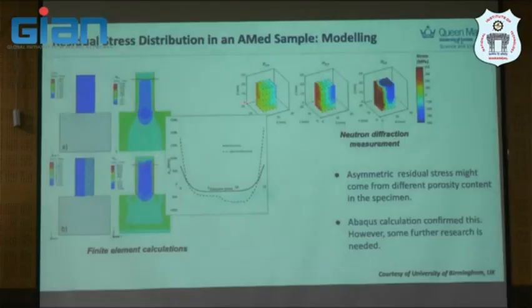So this one, what we try to do, we try to model what happened in the previous slide as well, looking at different microstructural content, assuming that this component has porosity preferred in one location. And this actually contributes to the asymmetry of the residual stress profile calculated in the Abaqus simulation here. And this actually confirms why further research is needed when you're looking at different components, different materials, different process conditions, to map all this information into your calculation or engineering design framework whatsoever.